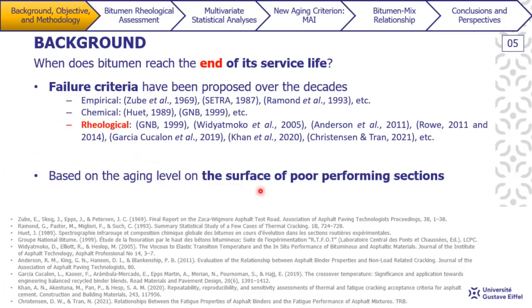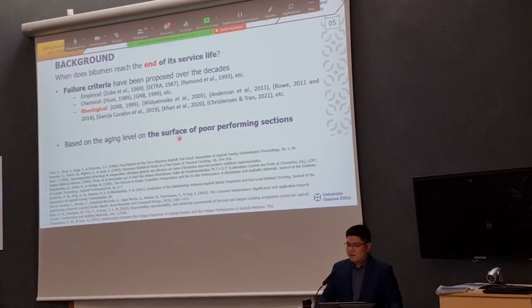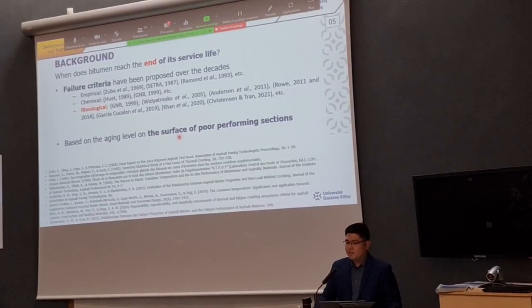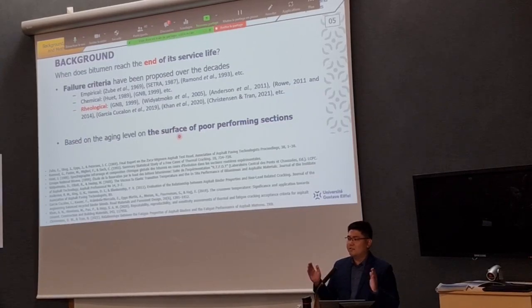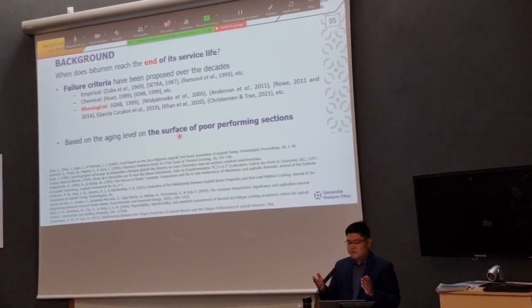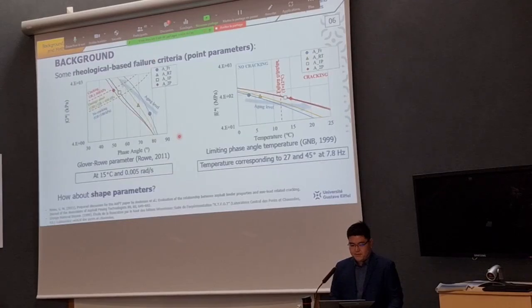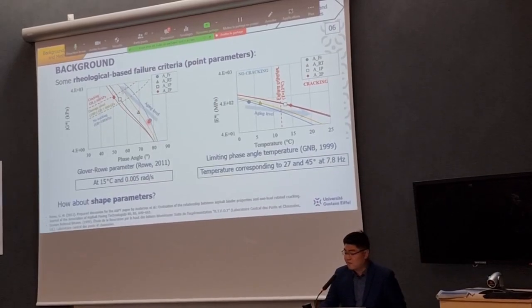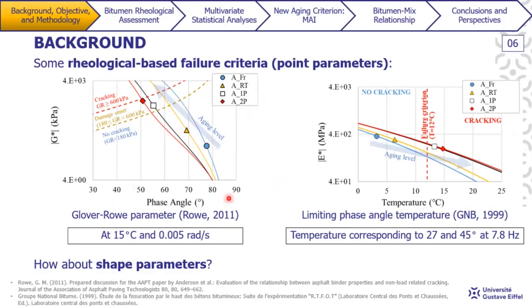And in this case, it's important to highlight the surface because that's where we get the highest aging intensity in our structure, according to the literature, and then we observe this intensity decreasing with pavement depth. So here are two good examples of some rheological-based failure criteria, and they are considered point parameters, and I will explain why. Here on the left, we have the Glover-Rowe parameter that was proposed by Rowe in 2011. And here we have the limiting phase angle temperature that was proposed in studies that were conducted here in France in the late 90s.